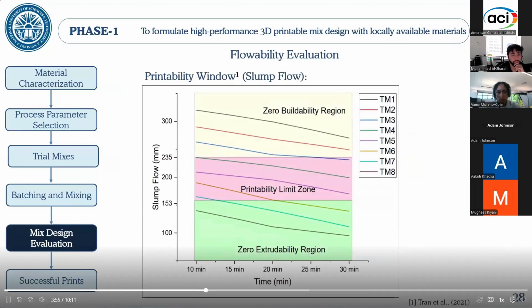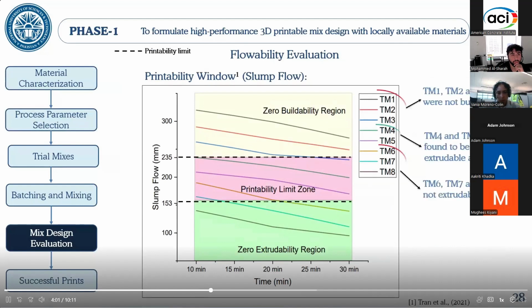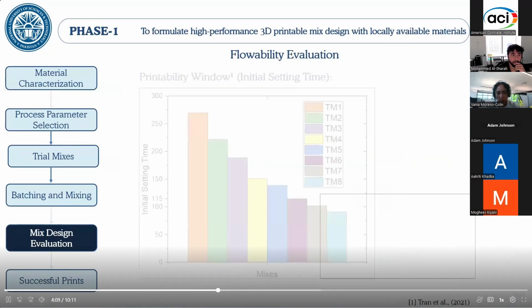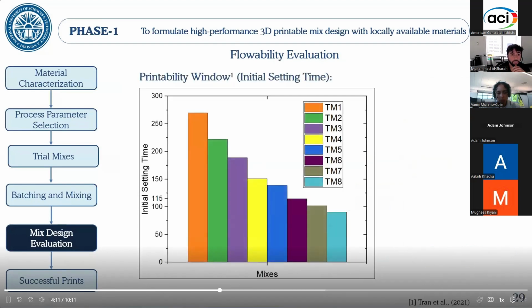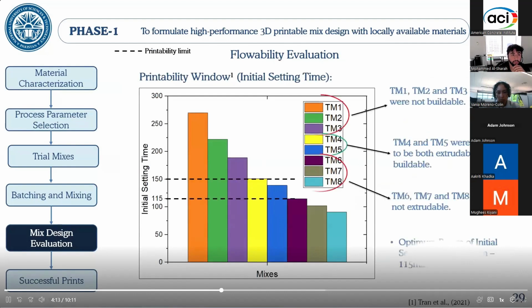Here, the first three mixes fell in the zero buildability region and were too flowable, while the last three were not extrudable due to being too stiff. Mix 4 and 5 fell in the optimum slump range, and mix 4 was chosen as a base mix due to superior print quality. The initial setting time test showed the same trend, and using that correlation, we drew an optimum range for adequate flowability.